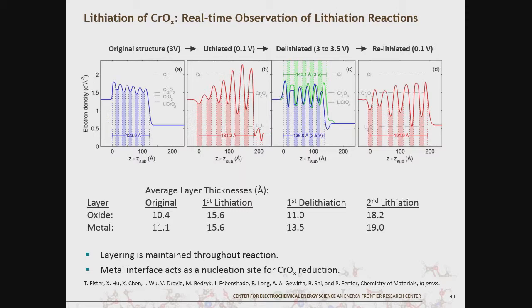There's a lot of information in here, but if you just look at the average layer thickness, you can see both the oxide and the metal increase and decrease and increase again, so you get the same behavior—some degree of reversibility. But you can also see at the metal layer, when it increases, it doesn't quite go back to the initial layer again. So what we can see here are some of the issues causing irreversibility in these systems.